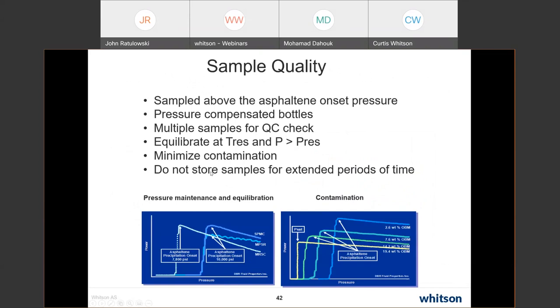One last thing that I really have to put in for asphaltenes, and we discussed a little bit before about storing samples, is it's really key that you get a good sample to do these measurements because it can be expensive. And if you get a bad sample of data, it's really not worth that much. So if you're doing live oil measurements for asphaltenes, make sure the asphaltene is sampled above the onset pressure. So you're going to keep it close to the reservoir pressure with minimal drawdown. You want to use pressure compensated bottles. We wish we had pressure and temperature compensated bottles, but there's no such thing right now. So this is better than nothing.